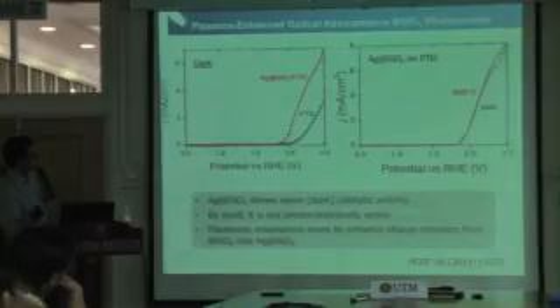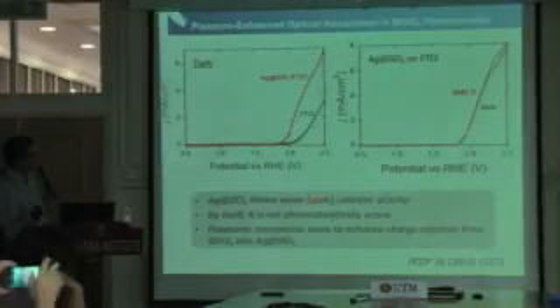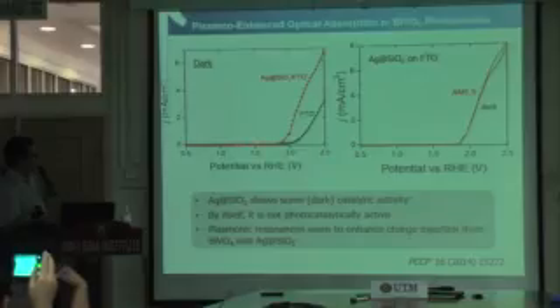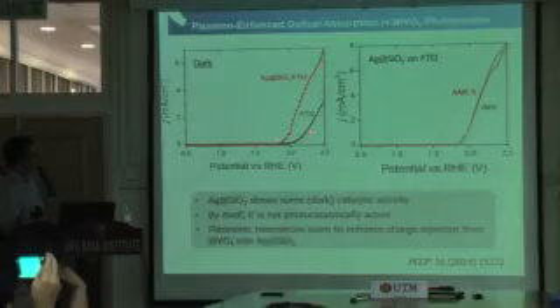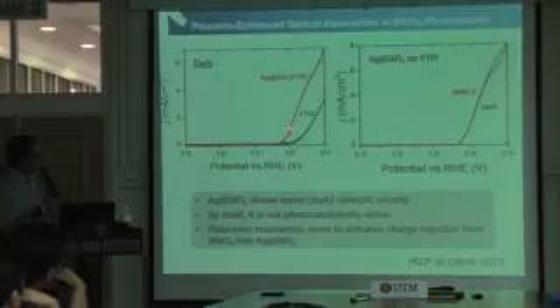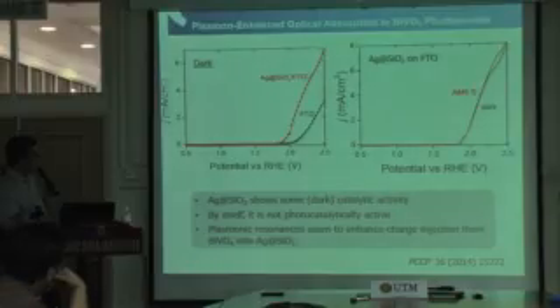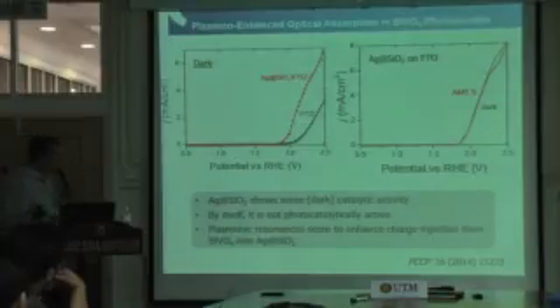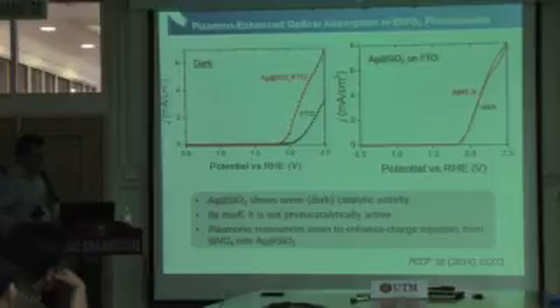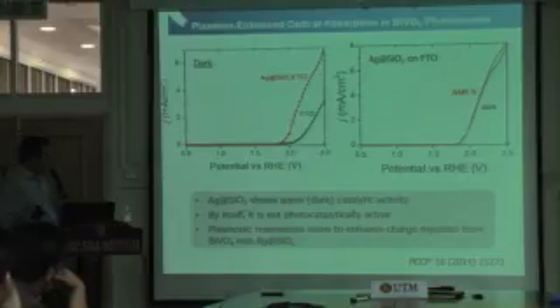It turns out that silver coated with silica shows some dark catalytic activity. Under dark, you can compare the bare FTO and silver silica-coated FTO, and you can see the shift of the onset of oxidation, suggesting some kind of catalytic activity. It's not a good catalyst, but it has some catalytic activity. But by itself, if you compare the dark and AM1.5, it's not photoactive. So it means that the plasmonic resonances that the silver silica creates, the field, seem to enhance the charge injection from bismuth vanadate into the silver silica. The more detailed mechanism is still under investigation, but we're still puzzled by that.